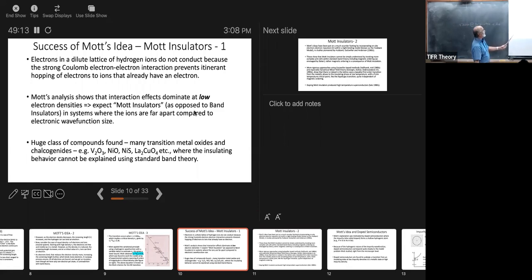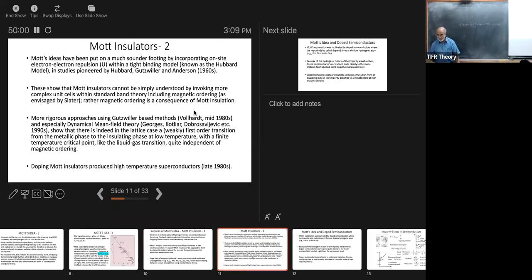Mott's analysis also shows that the interaction effects dominate at low densities. So we expect Mott insulators, as opposed to band insulators, in systems where the ions are far apart compared to the electron wave functions. So basically low density systems. And there is a huge class of compounds found in nature, transition metal oxides and chalcogenides like V2O3, nickel oxide, nickel sulfide, the high temperature superconductor parent compounds, where the insulating behavior cannot be explained using band theory. So Mott's idea has significant merits.